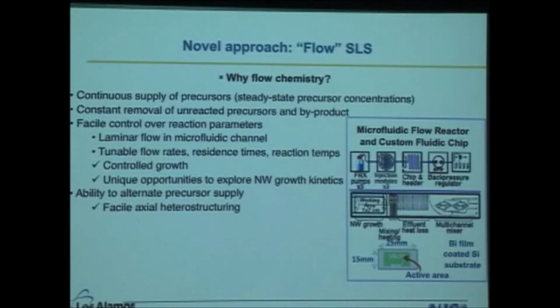So we developed a flow-based approach using a microfluidic flow reactor and a custom fluidic chip. We worked with a company to develop this chip. The chip has a fairly large working area, 1 by 2 centimeters, although the active area is quite a bit smaller than that. But the special thing about this chip is it allows us to open it up, put in a substrate that has our catalyst particles on it, close it, seal it, and do the flow chemistry at high temperature, 330 degrees C typically, in the liquid phase, and without leaking, sometimes.